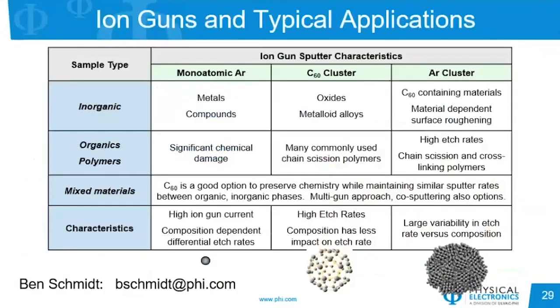And so what I hope to have shown is that based on different types of materials of interest, there are different factors that may play into which gun is going to be the most appropriate to achieve the answers that you're looking for. And as I've shown here, we have cases where inorganic materials can be best suited for monoatomic, depending on if we're cleaning or trying to depth profile. We can also use cluster sources as well, but we have seen some drawbacks with things like sputter rates and interface quality. Whereas for the organics and polymers, we know that monoatomic argon will cause damage to those materials, but we can use cluster sources to help preserve the chemistry for those profiles. And if we do have cases of mixed materials, then we can either use different guns for different layers within that material, or we can try using a single gun where something like a C60 might be appropriate to match the sputter rates of the inorganic and organic parts.